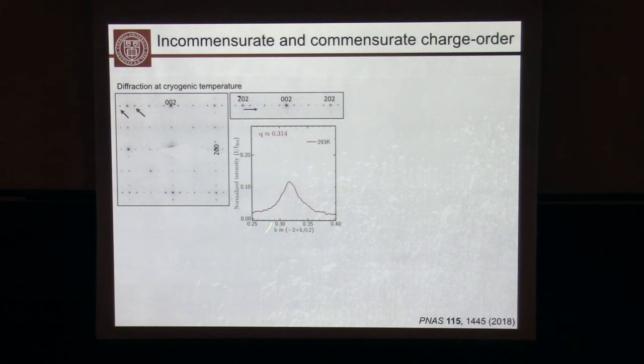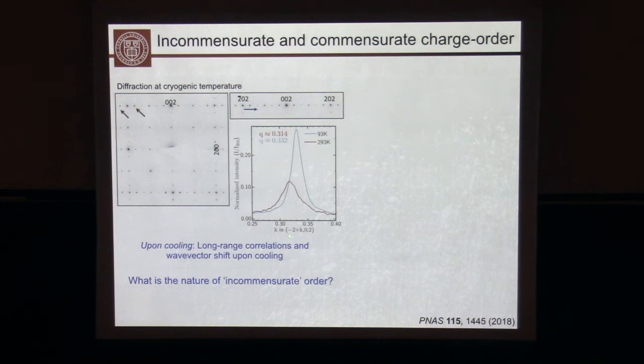This spot is in K space. This is at room temperature. It has a certain K value and a certain height. Now, when you cool, you see two effects. One, sharpening and strengthening of the peak, which tells you there's stronger long-range correlation. But you also see a shift in the position of the peak, and that tells you the wave vector shifts up on cooling. So the question we ask is, what is the nature of this incommensurate order as you cool the sample? Even at liquid nitrogen temperature, we are not quite at a third.